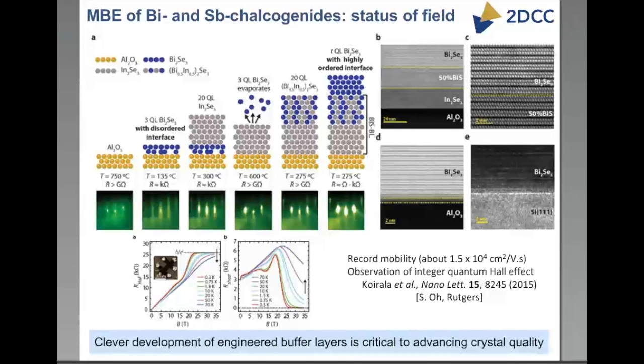They use sapphire as their substrate. They, for example, deposit 3 quintuple layers of bismuth selenide. They then grow an indium selenide layer on top, and then they heat up their sample so that the 3 quintuple layers of bismuth selenide, which are buried, apparently evaporate. They then grow a compound layer of bismuth indium selenide. And on top of that, they grow their bismuth selenide film. And when they do this, they get extremely good interfaces.